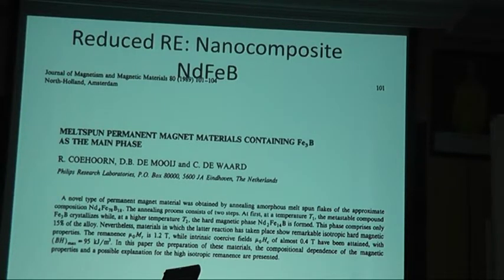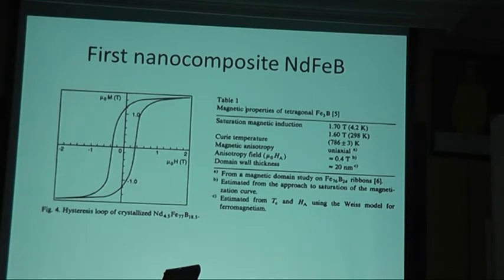But due to the dominance of iron boron, we get less coercivity, only 0.4 Tesla. So we increase remanence but decrease coercivity because we only use very little NdFeB. This is the hysteresis loop graph for 4.5% NdFeB. We can see here we get remanence of more than 1 Tesla. It is difficult to get more than 1 Tesla for NdFeB.